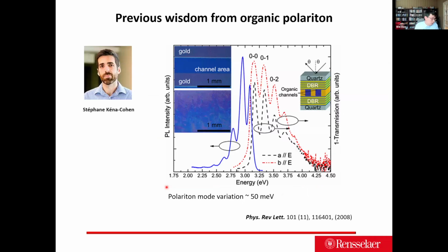I got a lot of wisdom from a close friend of mine, Stéphane Kéna-Cohen, from reading his work in Physical Review Letters back in 2008. They showed that by bonding gold and gold pre-patterned DBR mirrors together and fusing organic into those channels, they can form single crystal regions in the channels. Compared with without this gold bonding, where the organic becomes a really inhomogeneous material in the DBR cavity, the single crystal one shows quite a bit of homogeneous behavior, although the polariton mode variation at that time was 50 meV.